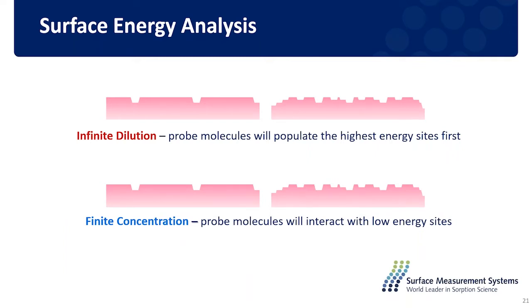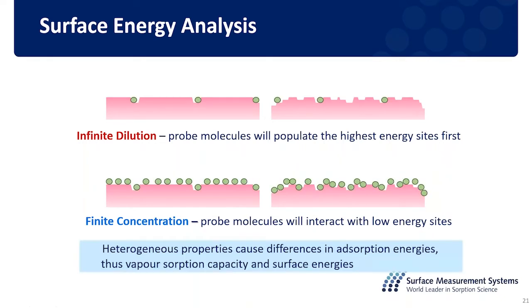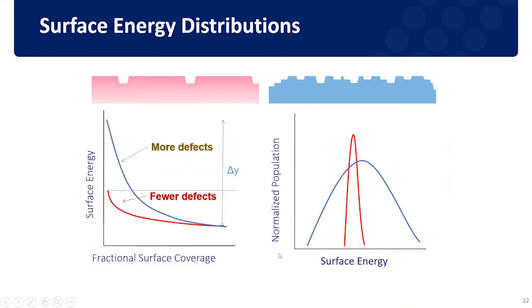So normally for the analysis of surface energy, we inject our probe molecule at different concentrations. When we introduce a very small concentration of the organic vapor, it will firstly cover the high energy sites. And when we gradually increase the concentration of our organic vapors, it will gradually cover the low energy sites. So we will have infinite dilution for the high energy sites, and then finite concentration for the low energy sites. And this is quite important because all natural materials have a heterogeneous surface, with both high energy sites and low energy sites.